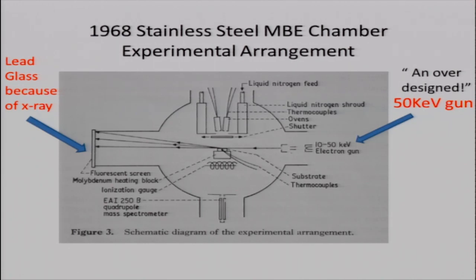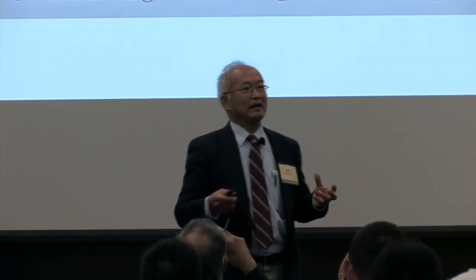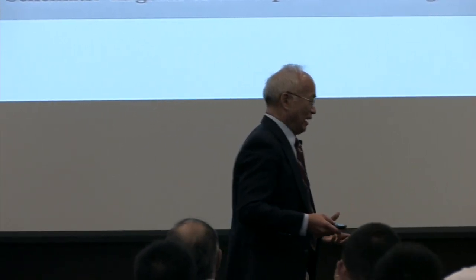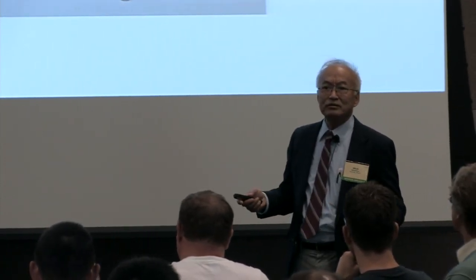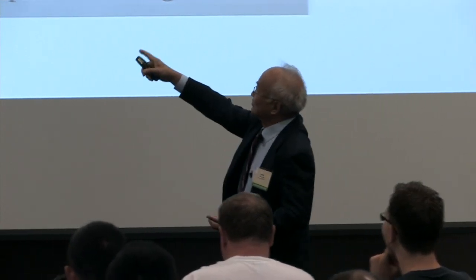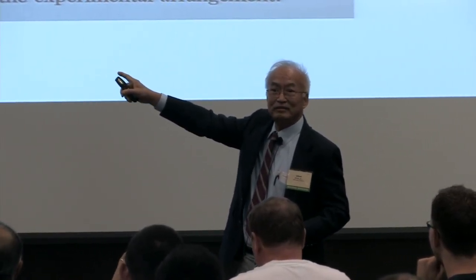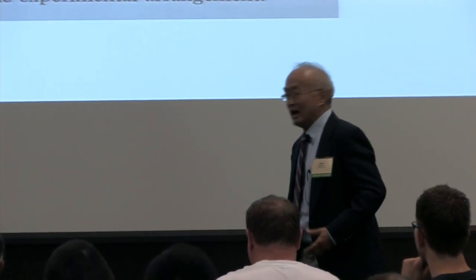We had to wind the effusion cells, and then here I bought a high energy electron diffraction gun, placed over here, and then diffracted over here. But when I first made the design, I over-designed. I used a 50 keV electron gun. I thought I could get better diffraction and look at better effect on the surface. But I didn't realize 50 keV produced soft X-rays. So I had to put lead glass in the diffraction screen. It's a nuisance.